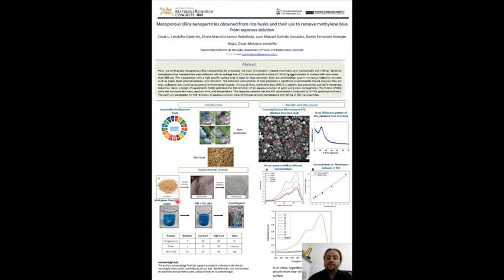A factorial design of experiments, 2^3, was used to evaluate the effect of different variables on methylene blue absorption by silicon oxide nanoparticles obtained from rice husks, for a methylene blue concentration of 2 ppm. For this, 2 levels and 3 factors were used. The working factors were absorption time, solution temperature, and nanoparticle mass. The work levels were high 1 and low -1. The explanation of each one of the levels, their respective factors of the experimental design, is shown in the table.